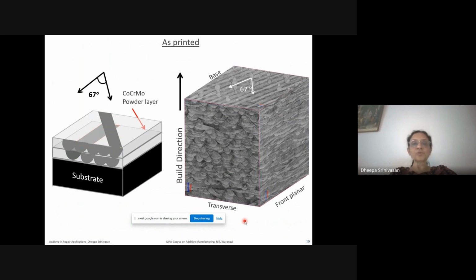Okay, so you're all familiar with the layer by layer welding and solidification process. There's a nice 3D etched microstructure of cobalt chrome moly. This is the build direction. The heat is extracted along this direction in this particular case. And there's a nice etched microstructure that the MTech student Kaustubh Bhavane actually etched, and then he has put together a collage.